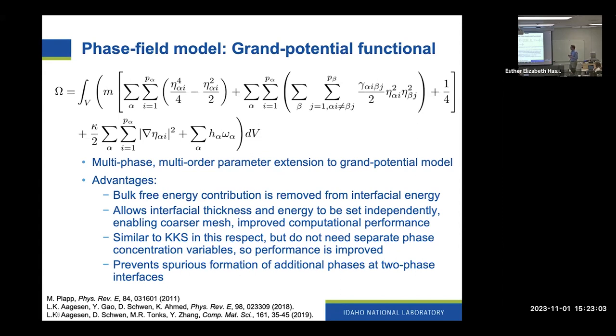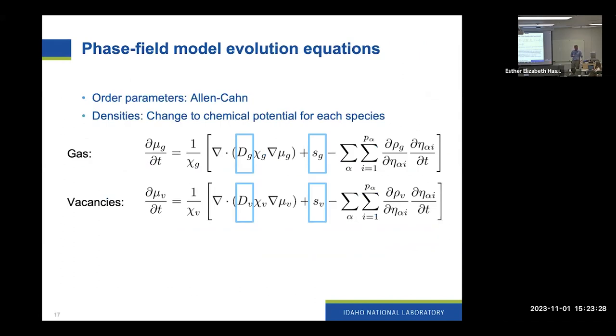But we don't, unlike KKS, we don't need separate phase concentration variables, which gives us improved computational performance. And then another nice advantage of this formulation is that it prevents the spurious formation of additional phases at the interface between two existing phases, which is something that's kind of plagued a lot of multi-phase models in the past.